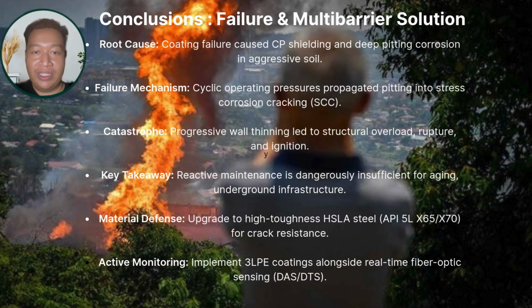For the conclusion, the root cause is coating failure causing CP shielding and deep pitting corrosion in aggressive soil. Because of that, as the failure mechanism, cyclic operating pressures propagated the pitting into stress corrosion cracking, or SCC. And the catastrophe happened. Progressive wall thinning led to structural overload, rupture, and ignition. The key information is that reactive maintenance is dangerously insufficient for aging underground infrastructure. So we need to replace it and upgrade to high-toughness HSLA for crack resistance, which means we need to replace the pipe with a tougher material, and we always need to actively monitor it by implementing 3LPE coatings alongside real-time fiber optic sensing.